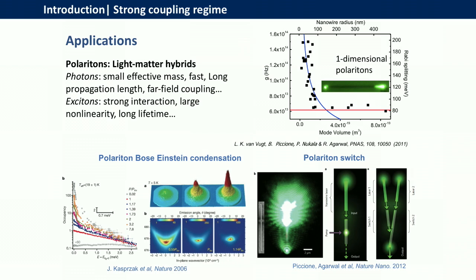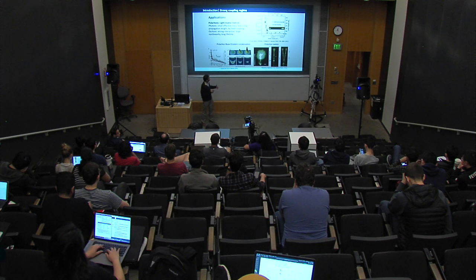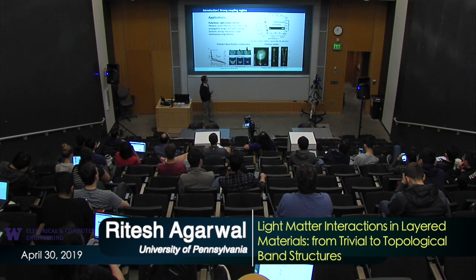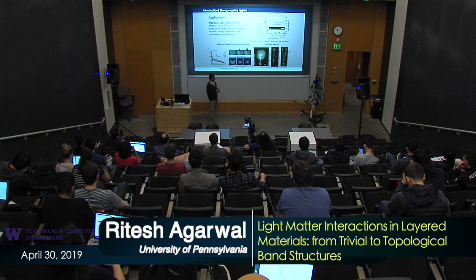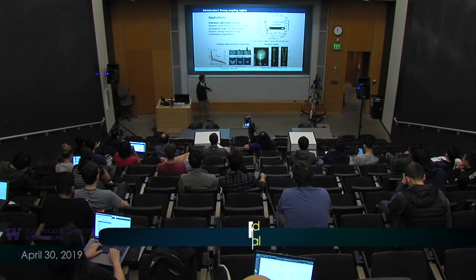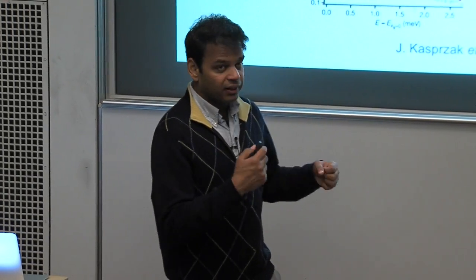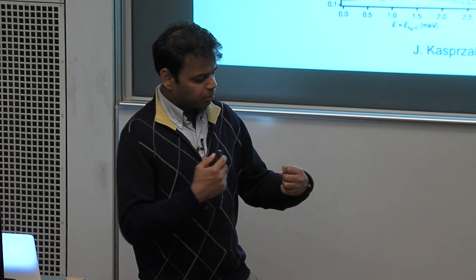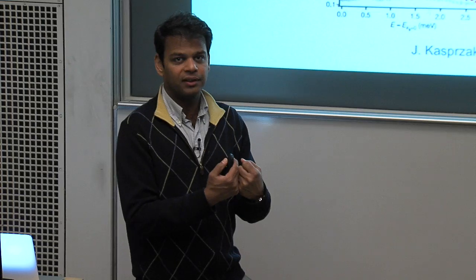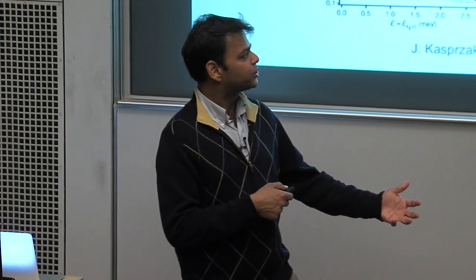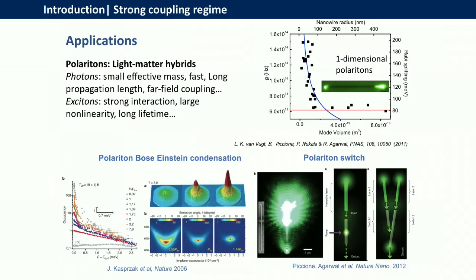where the light matter coupling strength becomes a strong function of the size. Because now we have this very strong light matter coupling strength, the exciton component is very strong, so nonlinearities are very strong. And by utilizing this, we were able to make an all-optical switch. Photons don't scatter off each other, but if we have polaritons with very large exciton component, excitons are material excitations, they can scatter off. But to scatter two excitons, you have to bring them really close to each other, like a few nanometer length scale. Because the length scale of a polariton is a few hundred, 100 nanometers or so in this regime, they can interact over longer distances and scatter off very strongly. So we made all optical switches and also did some very basic demonstrations of logical gates using this architecture.